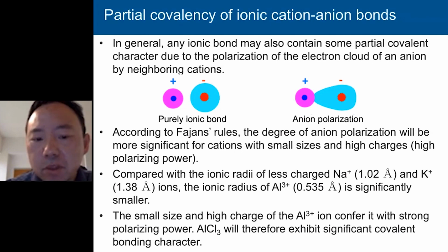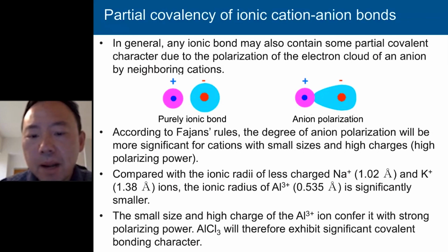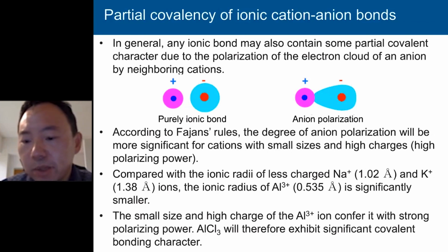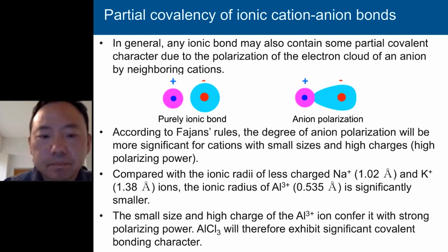According to Fajans' rules, the degree of polarization will be more significant for cations with small sizes and high charges. If you compare the size of aluminum in the 3+ charge state, it's much smaller than the sodium and potassium ions, and it also has triple the charge. This combination gives it a very high polarization power. Essentially, aluminum chloride will have significant covalent bonding behavior. As we will see shortly, this gives us some challenges in modeling.